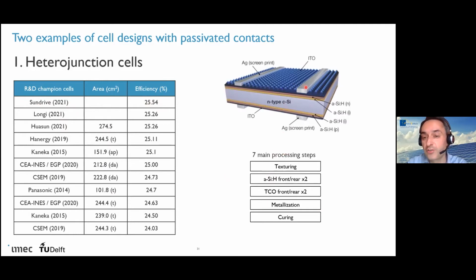Basically, you have to texture the wafer, then deposit the amorphous silicon layers twice, first on the front and rear, then deposit TCO twice at the front and rear. Then you do screen printing, metallization, and some curing, and basically your cell is ready. Because you have this symmetric cell structure, it's also very well suited for very thin wafers, which is an advantage.